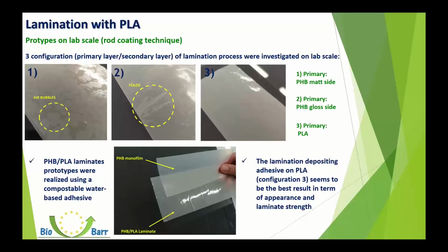We tried to make different configurations of the laminates in order to replicate what happens on an industrial lamination machine. In fact, we decided to make different prototypes, changing the choice of primary layer and secondary layer. As primary layer, we define the layer in which the adhesive is applied during the lamination. As you can see in the first two configurations, PHB is chosen as primary layer, from one side, matte side and gloss side. In the third configuration, PLA is chosen as a primary layer.